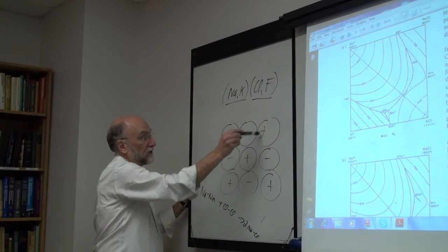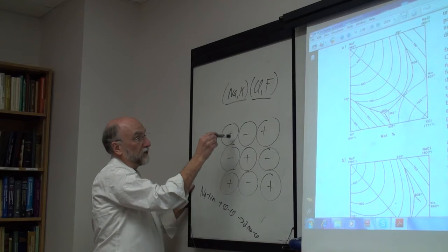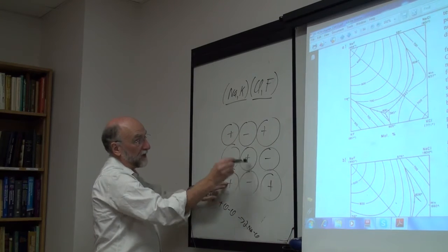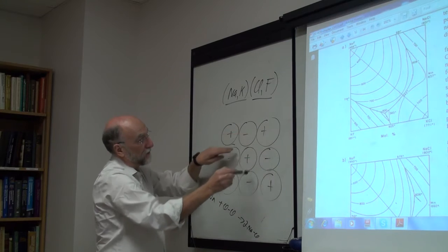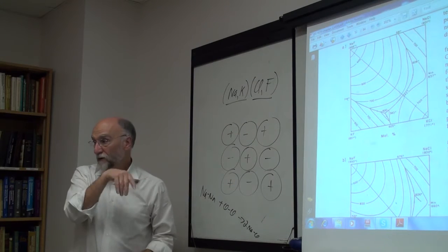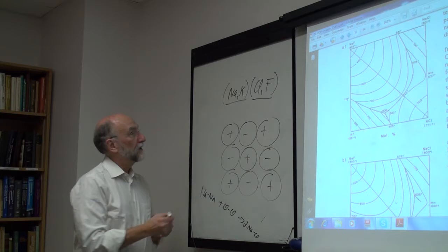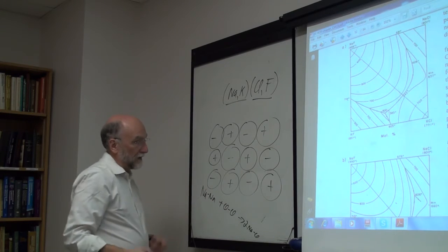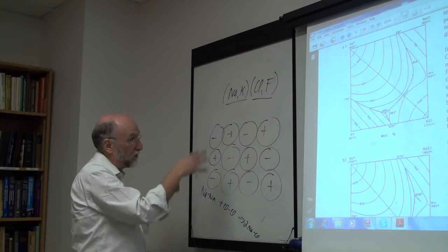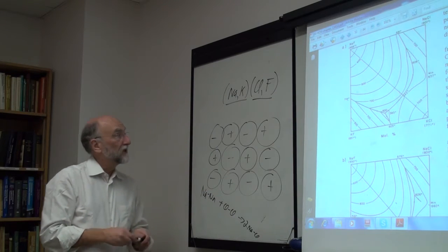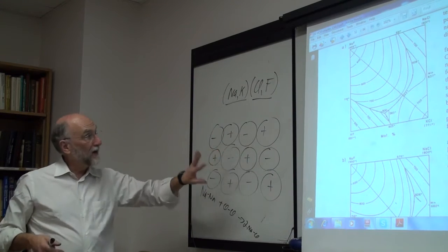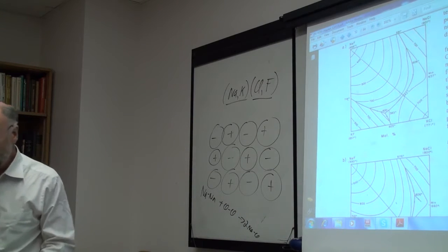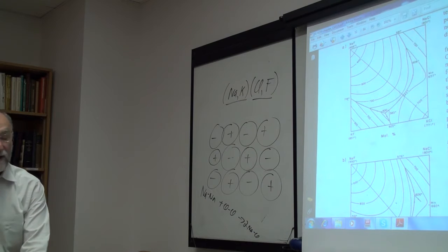On the positive lattice sites, sodium and potassium form one solution on the cation sites, and the chlorine and fluorine ions form another solution on the negative ion sites. Basically all your sublattice models are based upon that. You have a solution, sometimes a random mixture, on each sublattice. Each sublattice forms its own sort of solution, although you can get some crossovers sometimes, as we'll talk about later.